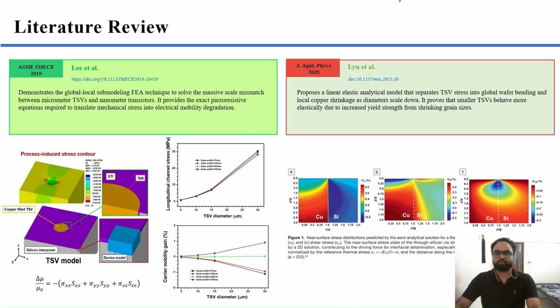Now let's move to the figures. So look at this color map. They show the stress that builds up in silicon right along the TSV when chips cool down. Red means high stress, blue means low or even compressive stress. The left map shows stress pushing upward and downward, called axial stress. The middle shows stress pushing outward in all directions, that is radial stress, and the right map shows twisting or shearing stress near the top edge of the TSV.